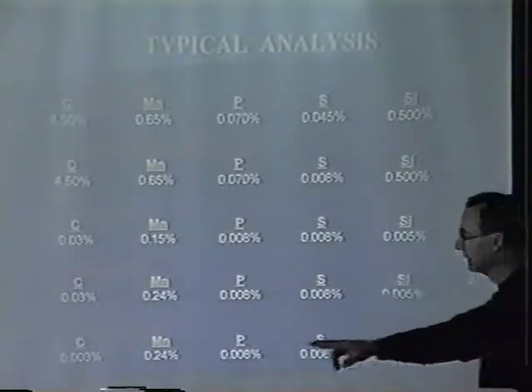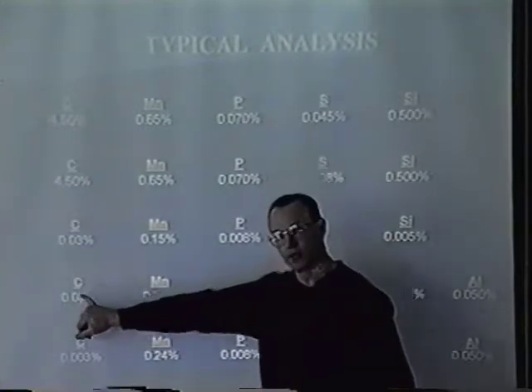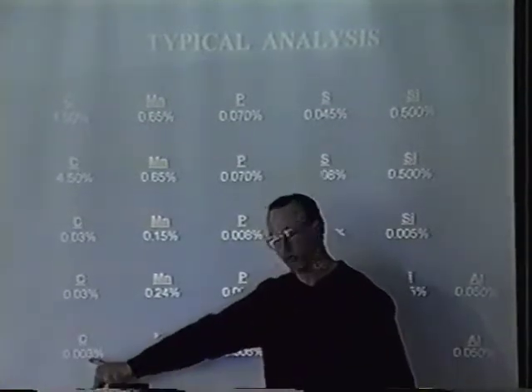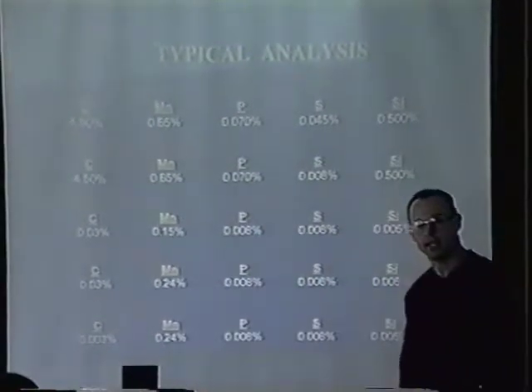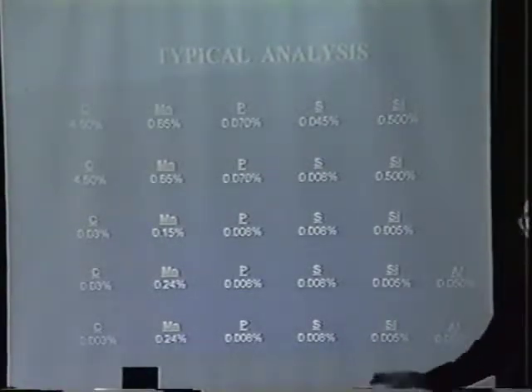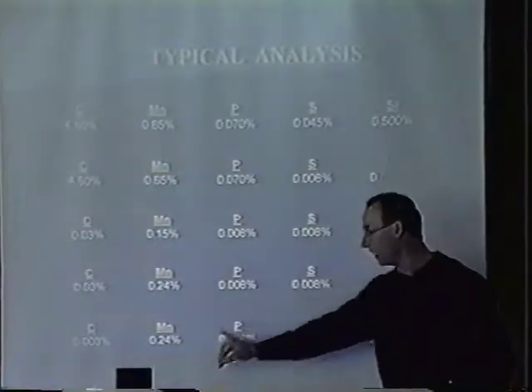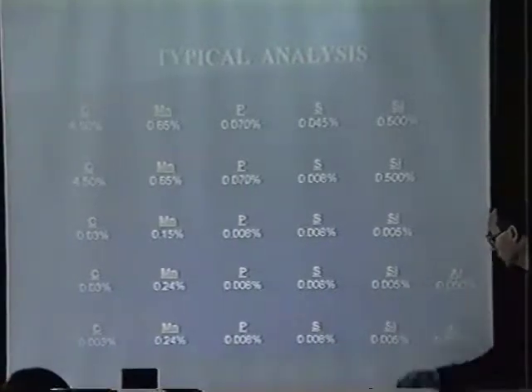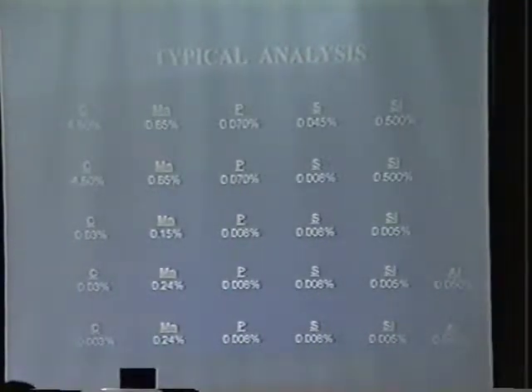And let me jump ahead here to my chemistry. Down at the bottom, you can see we've gone from a 0.03 carbon in the furnace down to a 0.003 carbon at the degasser. And we have not affected the phos, the manganese, the sulfur, the silicon, or the aluminum at all. We've basically just sucked all the carbon out with the degasser.